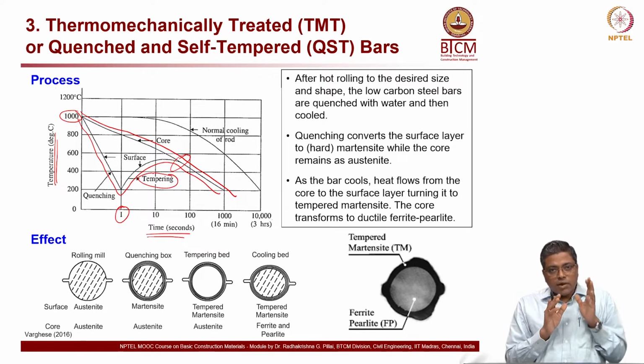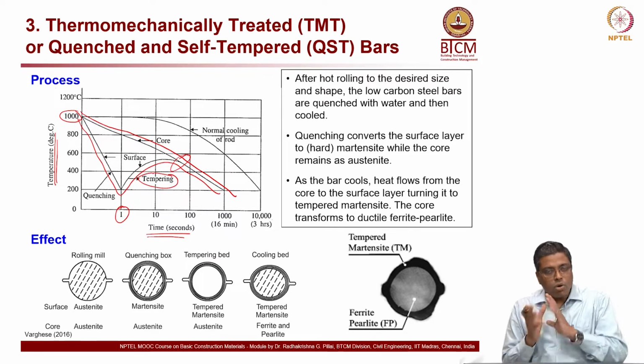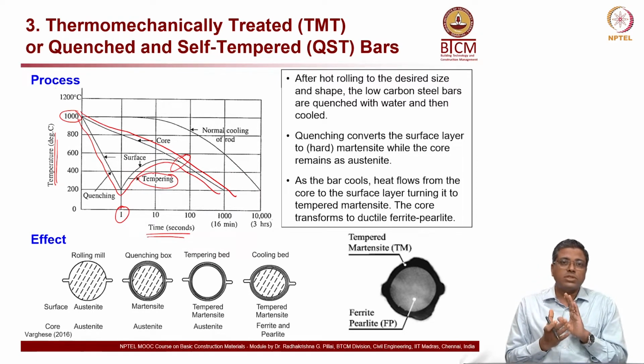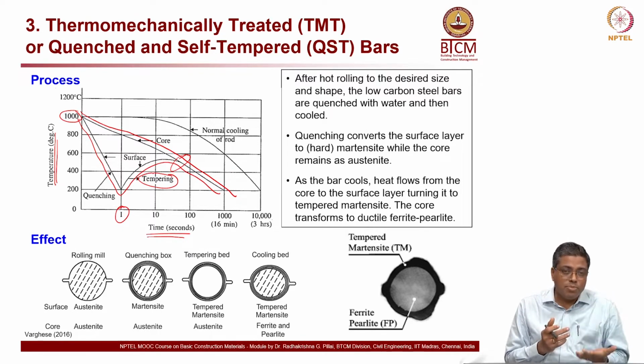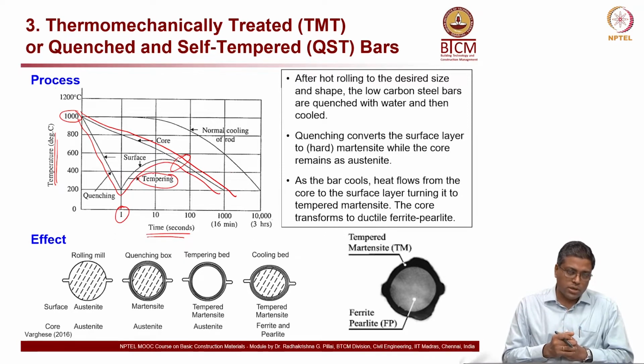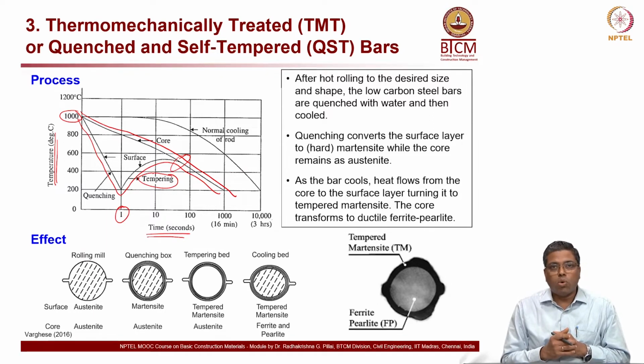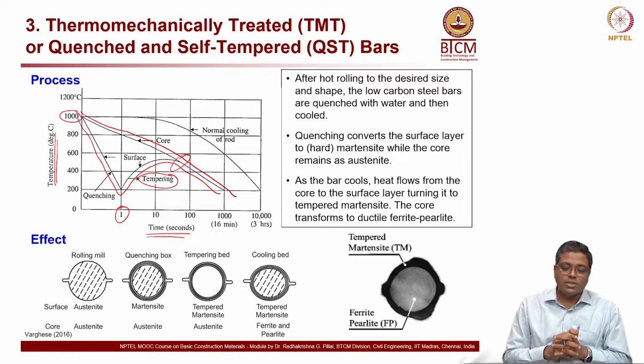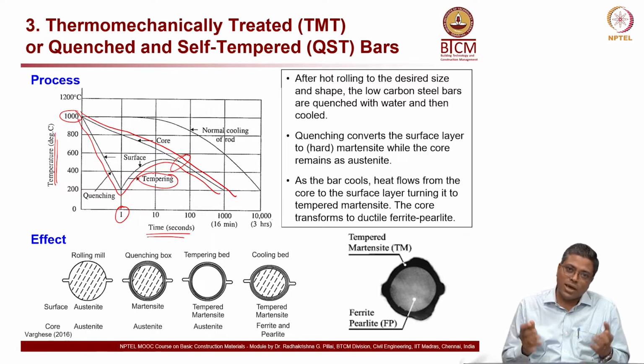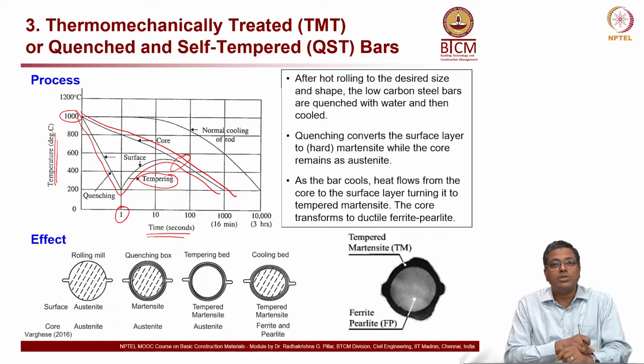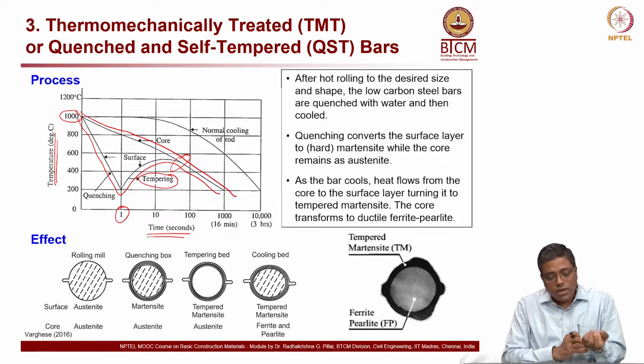So the surface temperature is different from the core temperature during the manufacturing process. The surface gets quenched, and then it gets tempered because of the heat coming from the core of the steel bar. So we call it self-tempering. That's why the name quenched and self-tempered steel comes from, QST. And ideally speaking, QST is the correct terminology and not TMT. TMT is like Maggie, we say, no? Somebody started calling it Maggie, we all call it Maggie. But actually the correct name of Maggie is noodle.